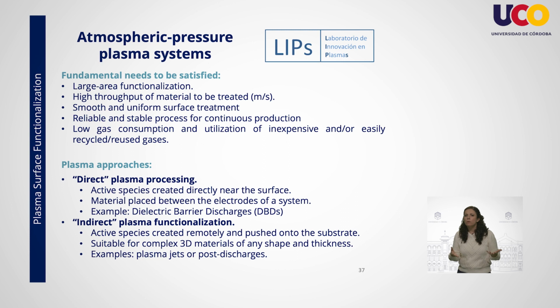Which are the plasma process approaches for this purpose? On the one hand, direct plasma processing, where the active species are created directly near the substrate, with the substrate placed in between the electrodes of a system. One common example of this approach is the use of the dielectric barrier discharge. On the other hand, indirect plasma functionalization, where the active species are created remotely in the plasma and pushed onto the surface. This second approach is also commonly known as atmospheric pressure plasma jet or post-discharge deposition process, which are suitable for complex 3D substrates of any shape and thickness, as there is no electrode spatial confinement.